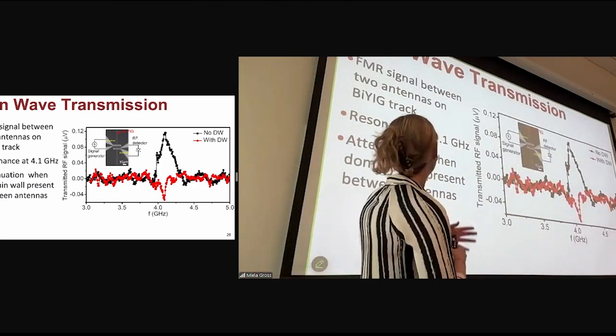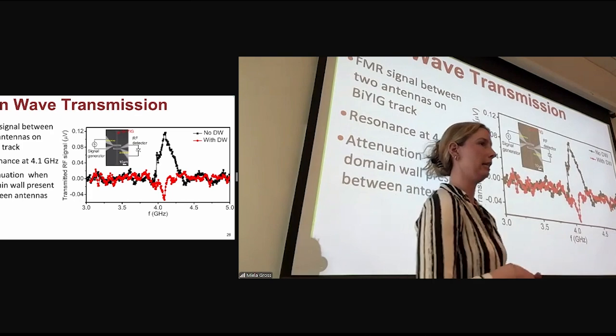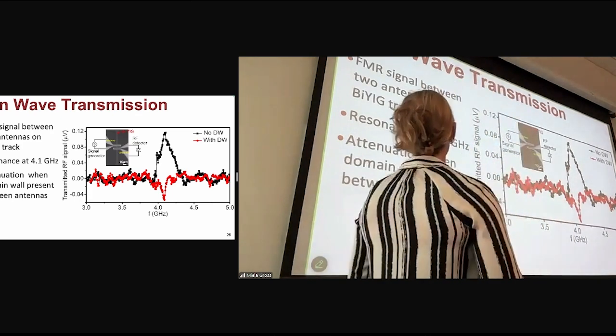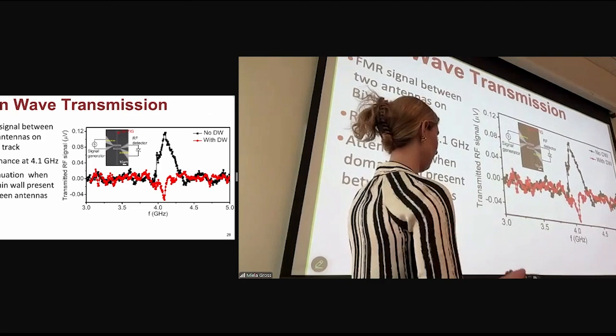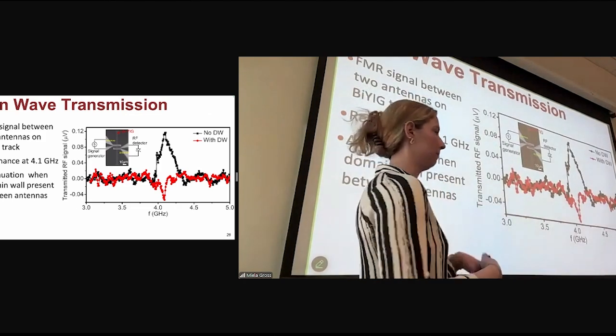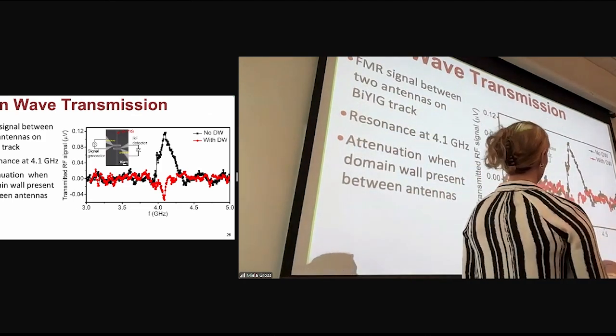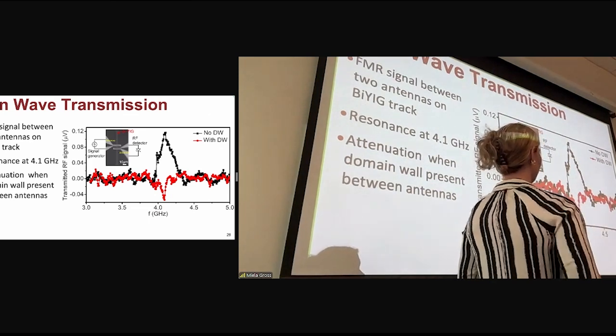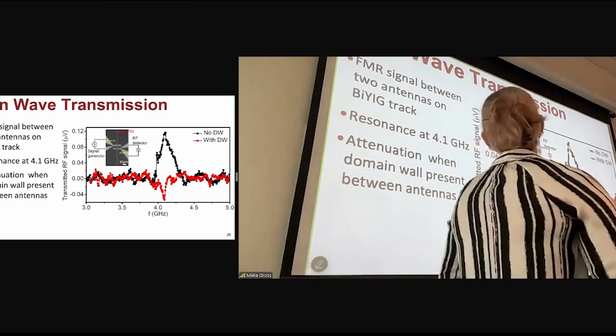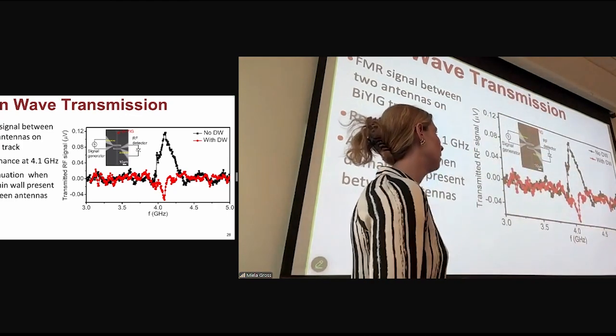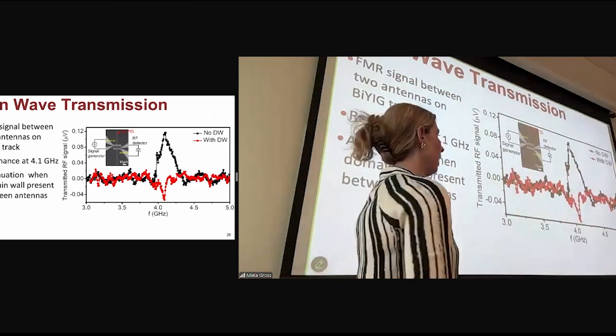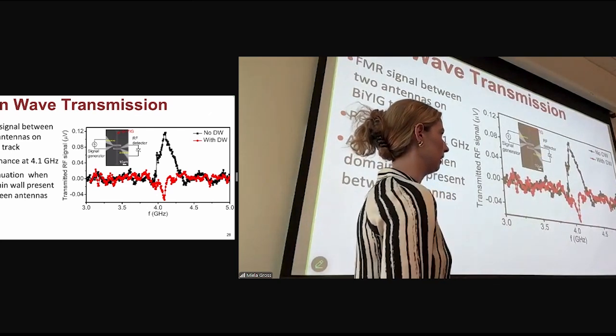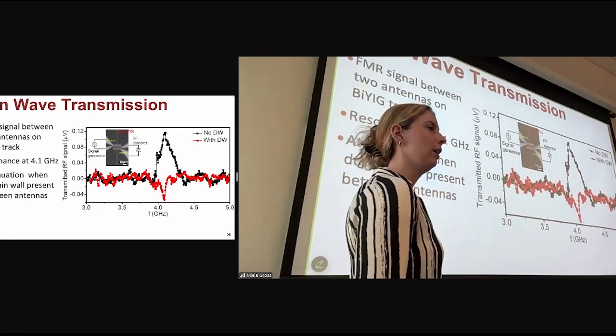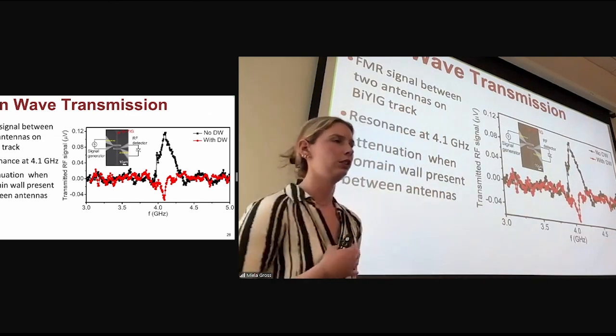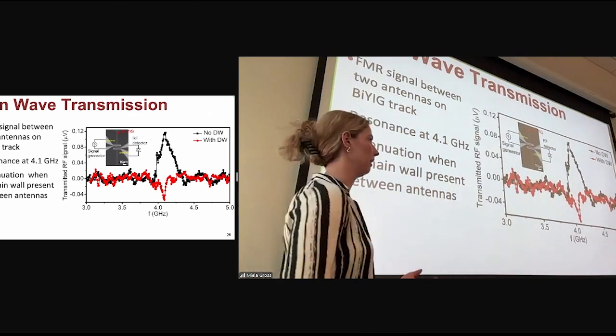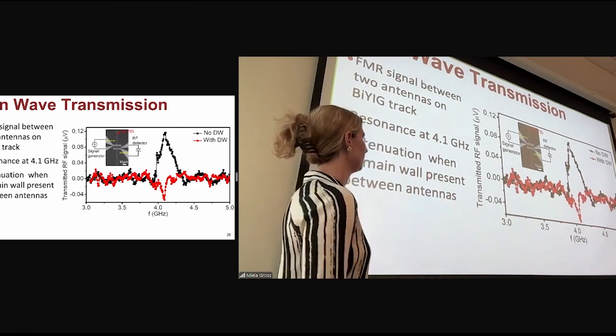So after that, we wanted to look at the spin wave transmission between two antennas to see if we could even excite spin waves. So we sent in an FMR signal between the two antennas on a bismuth YIG racetrack with it all magnetized in one direction. And between 3 and 5 gigahertz, you see a peak around 4.1 gigahertz that shows, okay, something's going on. We're exciting some magnons. We then wanted to repeat this experiment with the presence of a domain wall between those two antennas, and we still see that same resonance peak around 4.1 gigahertz. However, it's significantly attenuated, which tells us that there's some sort of energy exchange between the spin waves and the domain wall that was between the two antennas.